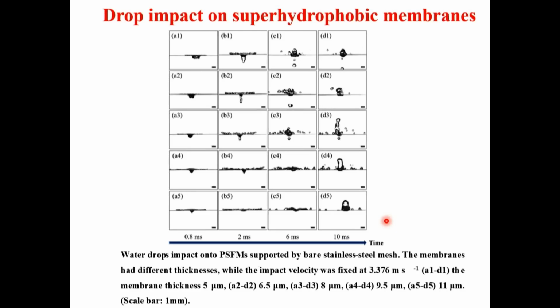So then you can also start to increase thickness, and when you increase thickness, intuitively it's clear that you can diminish penetration of water through the membrane, and indeed it happens, you see less and less water penetrates. You have a pretty chaotic phenomenon on the top when you go to higher velocities, but the main thing is that you do protect the lower part from water penetration.